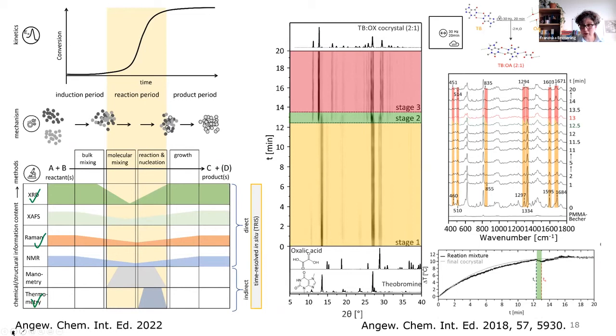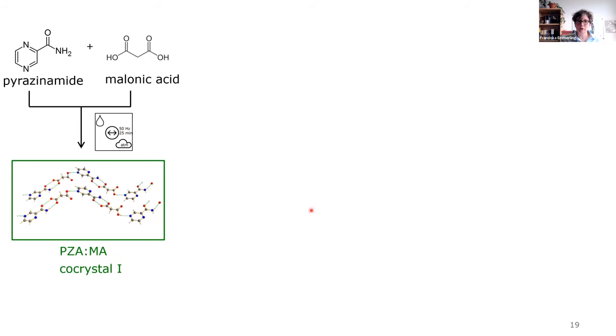Okay, this was an example where we knew what's happened, and this is another molecule we studied intensively. It's pyrazinamide, an anti-tuberculosis drug, and we reacted it with malonic acid, and we ended up with this cocrystal, which was already known. Afterwards, we performed different liquid-assisted grinding experiments looking for new polymorphs of this compound. We never found any, but then we investigated the process in situ, and here you see a slightly different picture.